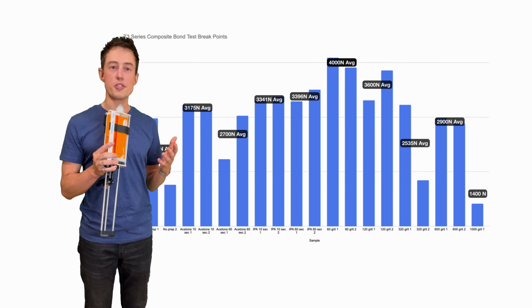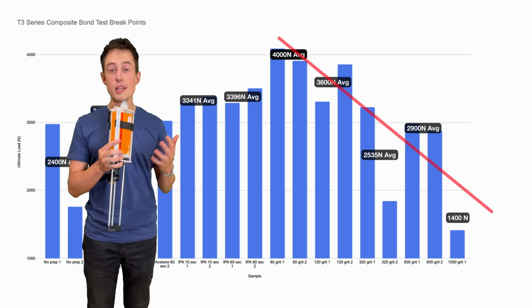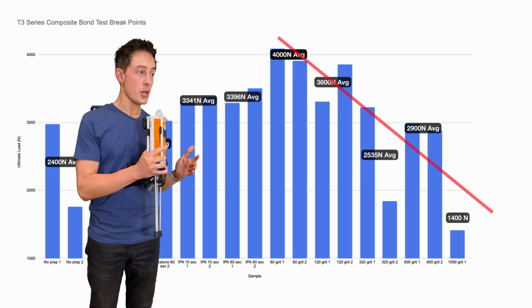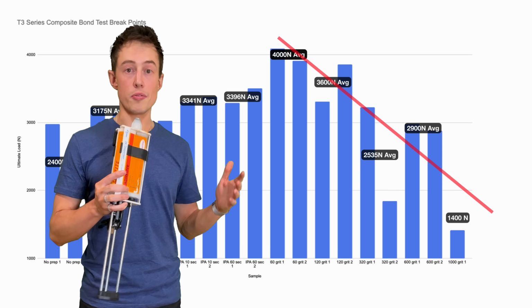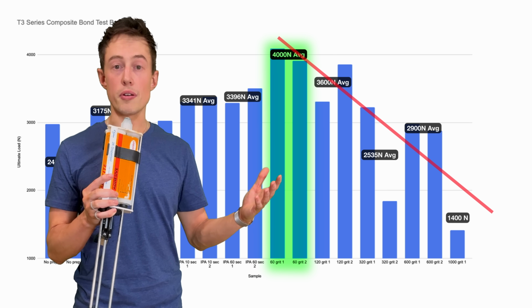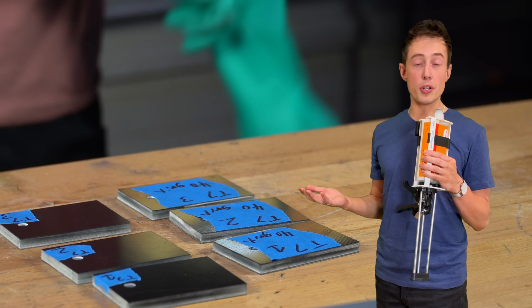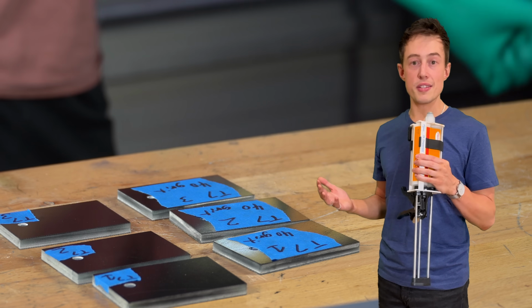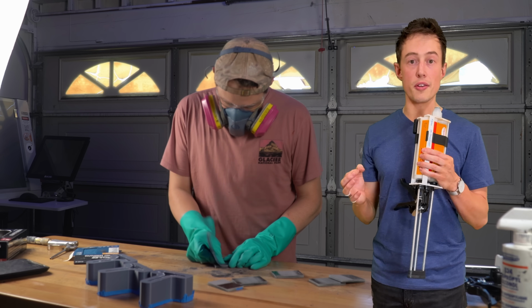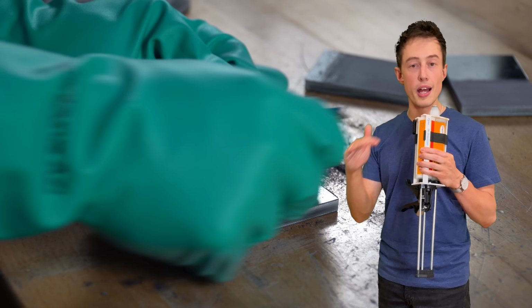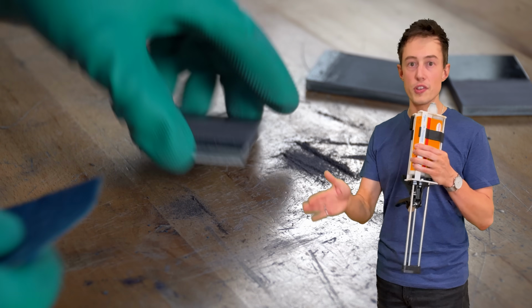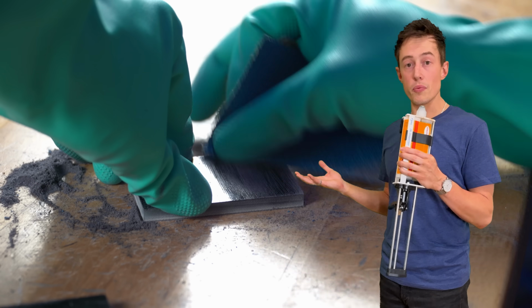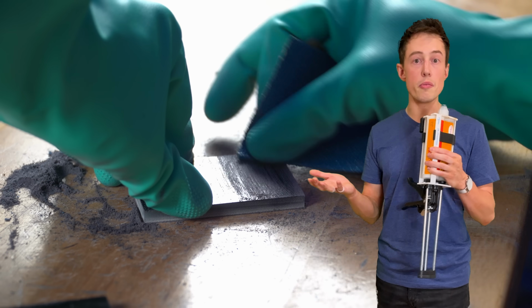Next, I followed some logic from my original testing, which seemed to indicate that lower grit sandpapers perform better. We've been messing around with 60 grit, let's go lower. How about 40? The nice thing about lower grit sandpaper is it goes a lot faster. There are really big grooves that are created here, and so we etch away a lot more surface area every time we move the paper across. It might be a win-win. Maybe this is how we do big composite parts.